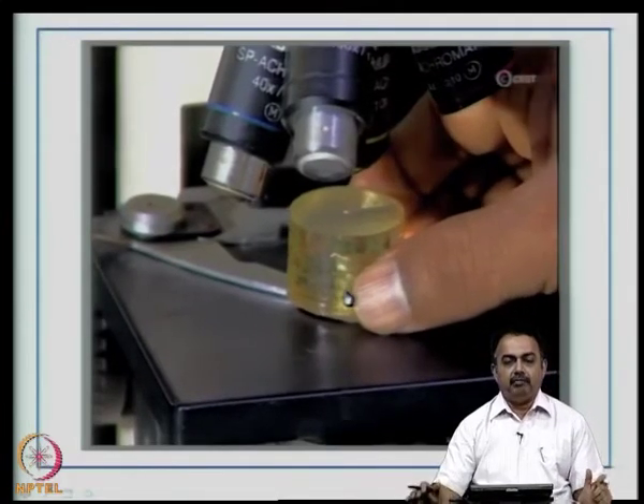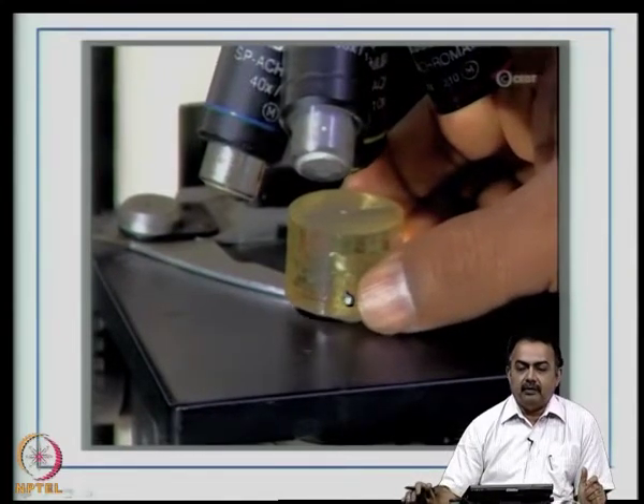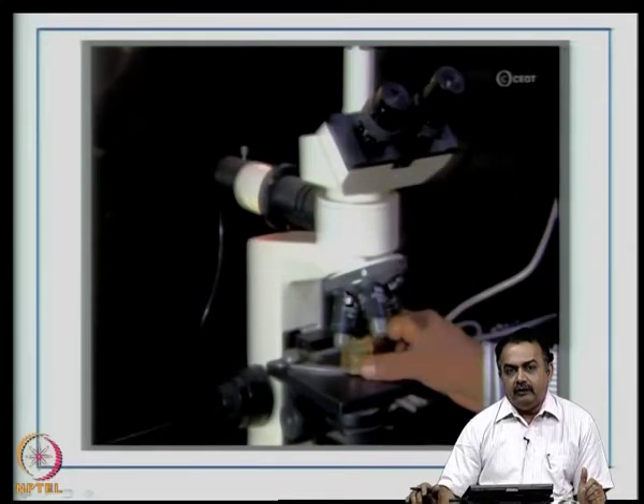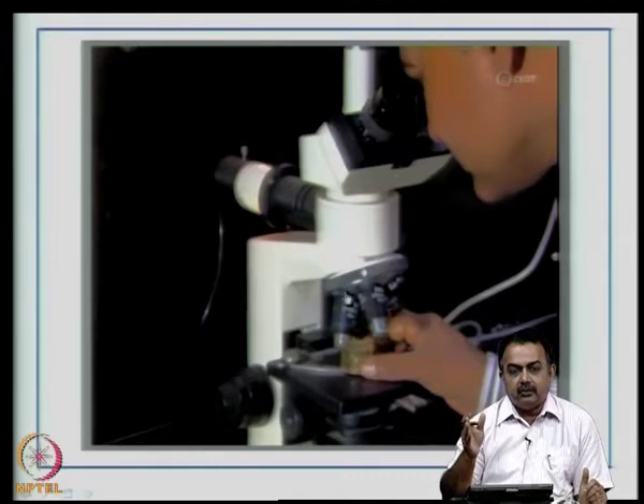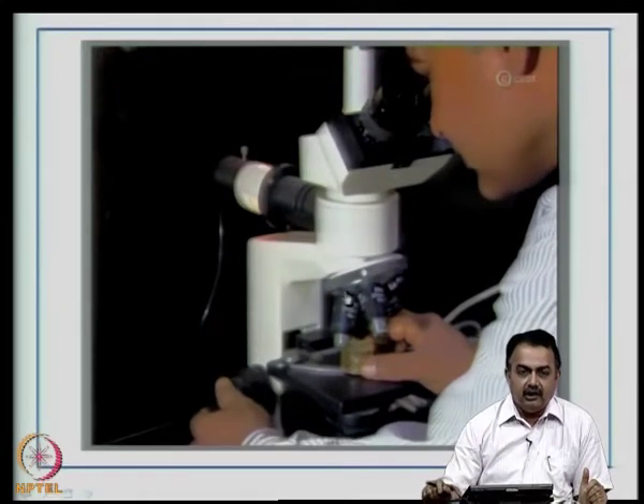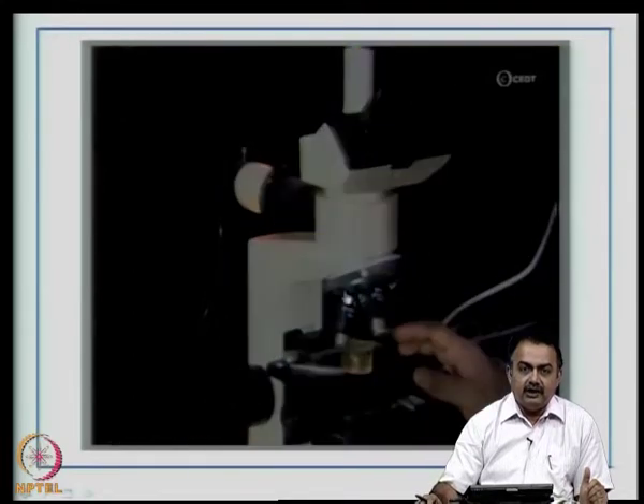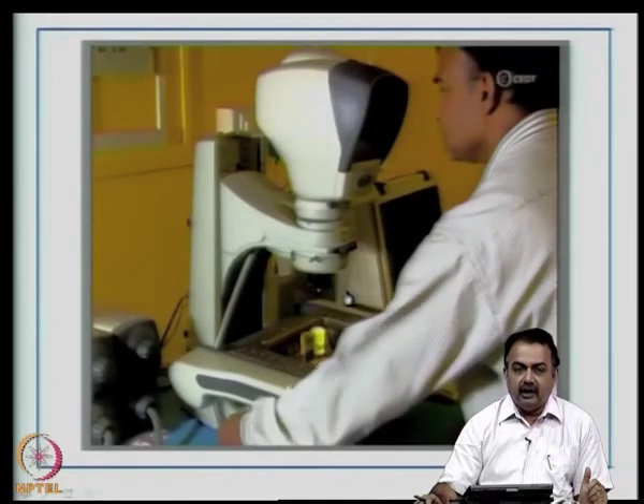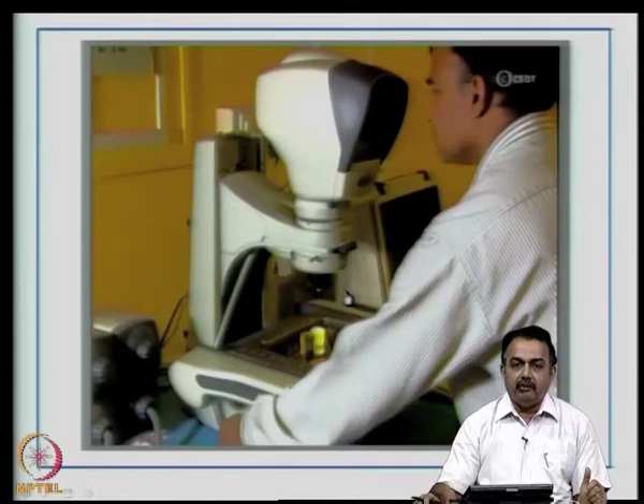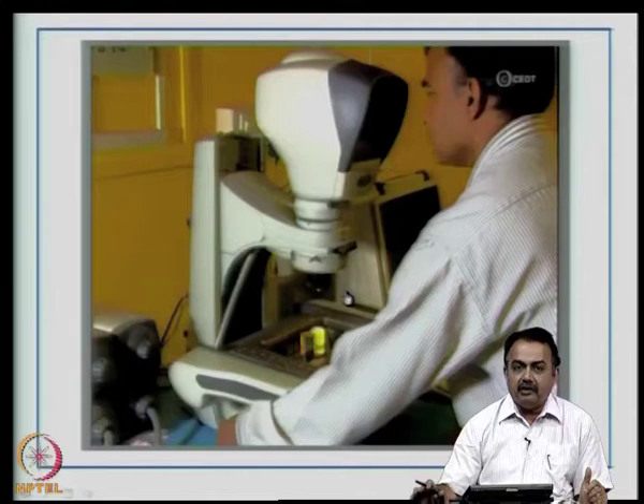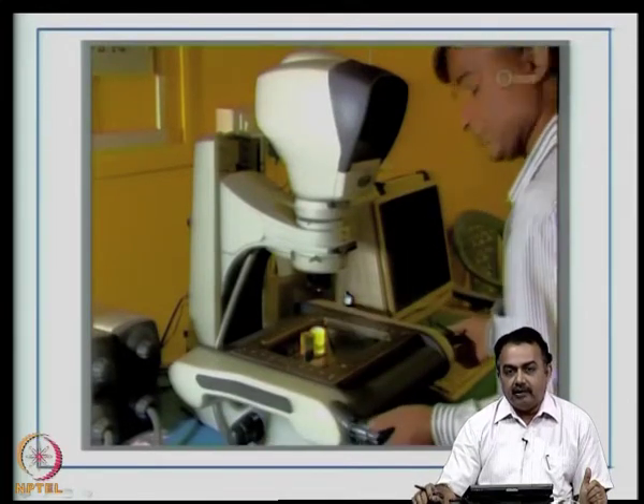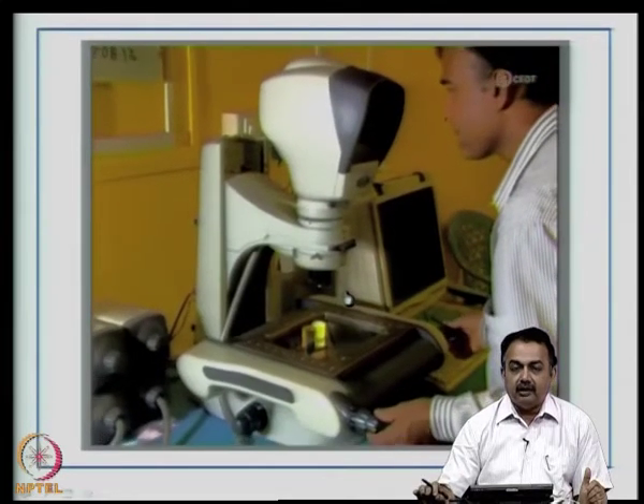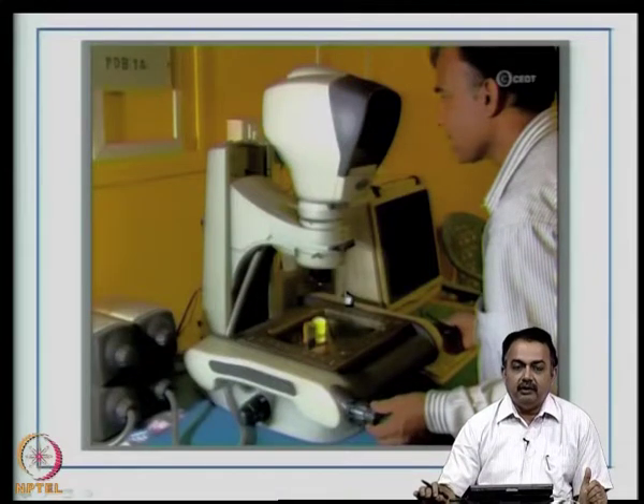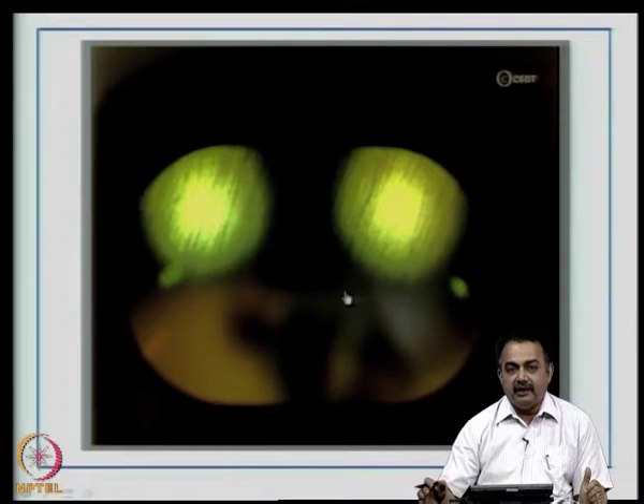Typically this is an important and a must process in volume manufacturing also. When the drilling process starts for certain panels, they will drill these coupons of various drill sizes, and then the quality team will have to take samples for each of these coupons or earmarked areas, and then they have to report back to the manufacturing line about the quality of the deposit and how much tighter control they have in the deposition rate, because the electrical performance is going to depend on the thickness of the copper deposit that the manufacturer can provide you, because you can't plate more thickness of copper than necessary, and also you can't have lesser thickness than the specified.